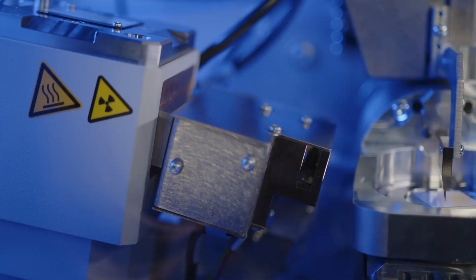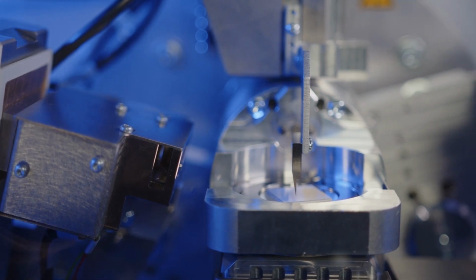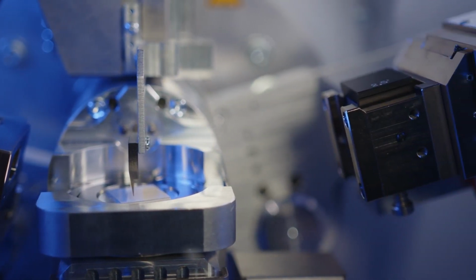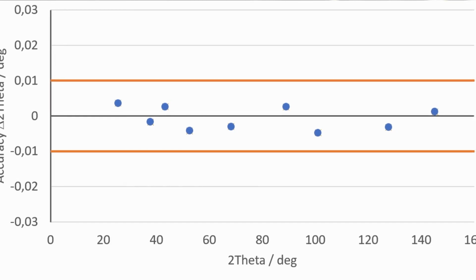Like its predecessor, the D2 Phaser, the D6 Phaser is a great instrument for powder X-ray diffraction experiments. The Phaser goniometer allows the collection of high-quality data with a small measurement radius. Combining the small radius with a new 1.2 kilowatt generator and LynxEye XE-T results in signal levels rivaling the most powerful floor-standing equipment. The Bruker accuracy guarantee ensures that all peaks on the standard corundum sample included with the instrument will be within 0.01 degrees of their anticipated peak locations, meaning that not only the individual components, but the system as a whole is capable of extremely accurate measurements.